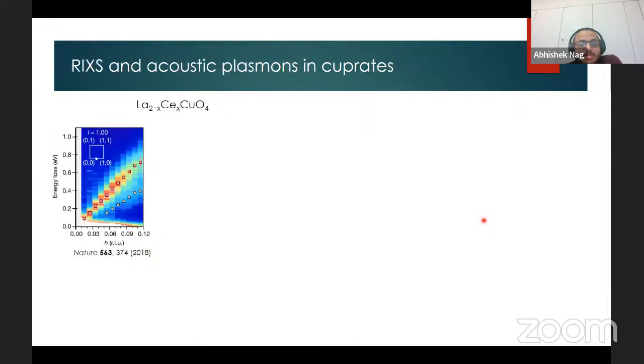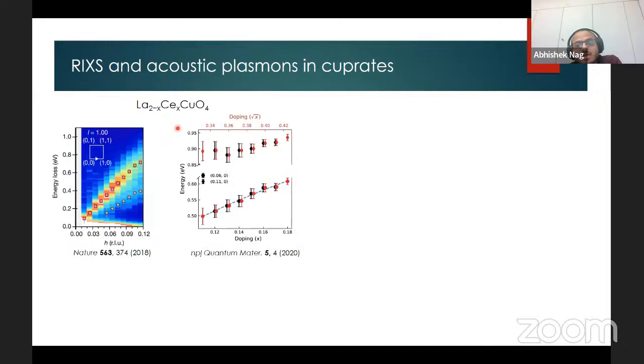The breakthrough came in 2018 when Wei-Sheng Lee's group from Stanford University discovered the presence of acoustic plasmons in electron-doped cuprates using a technique called resonant inelastic X-ray scattering (RIXS) at the copper L-edge. A following work, again using copper L-edge RIXS, showed that the doping dependence of the plasmon energy did not follow the expectations of a free electron model, which is a clear indication that the plasmons carry the effects of the electron correlations that define these cuprates.